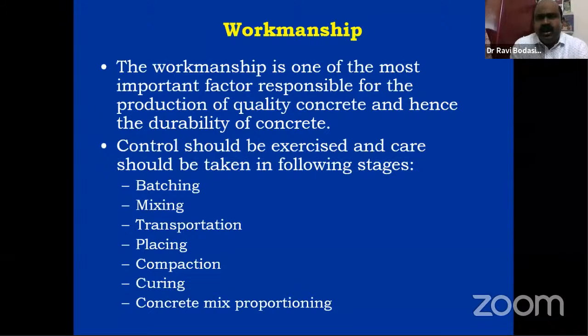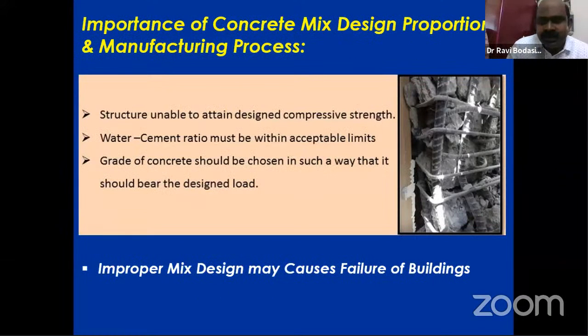Coming to the major factor, workmanship. Workmanship is one of the most important factors responsible for the production of quality concrete and for finishing the concrete. We have discussed batching, mixing, and transportation, all these parameters. We require at least 100% skilled workmen to address the durability of the structure. If the mix design is not properly followed, you see there is no 20 mm coarse aggregate in the element. After breaking and chipping, we identify that the column did not take enough load because no coarse aggregate was mixed. These are all the factors that will affect it.